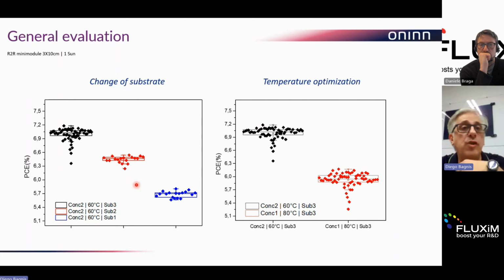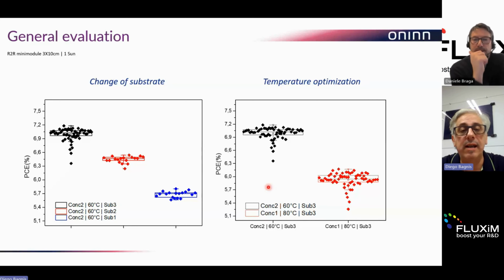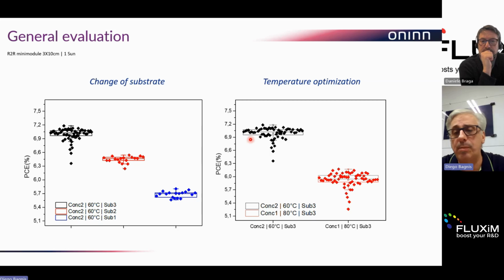And if we try to give a general evaluation for this kind of formulation, we take the higher concentration, the best condition, we take the best temperature condition, and we change the substrate, similar in sheet resistance, the IMI or the ITO, as we prefer to call it. On this side you see there is a big difference. On the other side, if we take a different concentration and a different temperature but the same substrate, it is clear that the substrate makes the main difference. And here, if we maintain the same best substrate but change the condition slightly, you see that there is also a big drop.